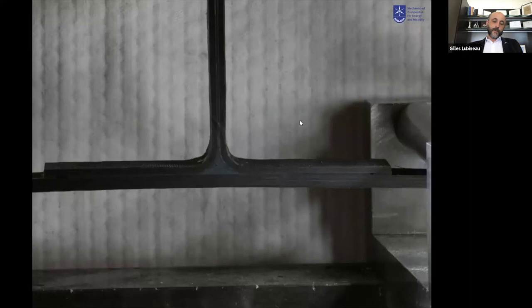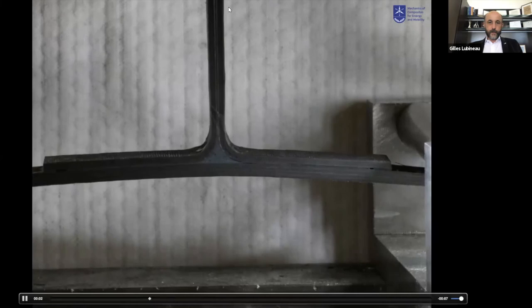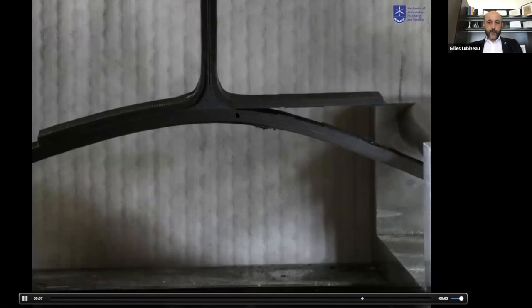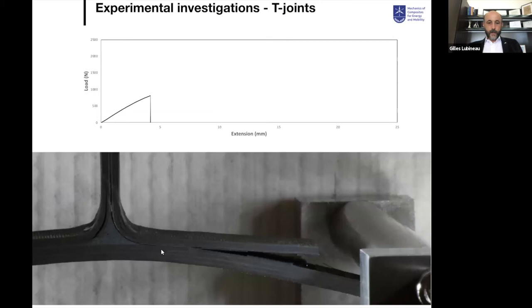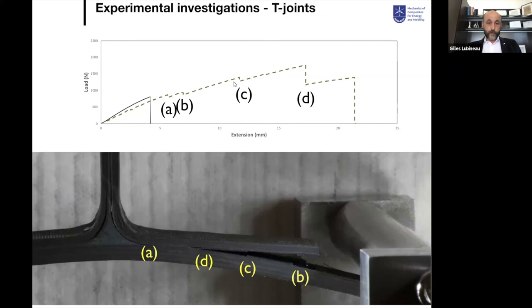Since it works in both mode 1 and mode 2, we applied it to more complex structures — for example, a stiffener T-joint. You can see crack propagation at the root of the T-joint and development of multiple ligaments at the laser-treated interface. The load-displacement curve without laser patterning shows a brittle response, while after laser patterning you see a much-improved curve that correlates well with the different bridging events appearing during failure of the T-joint.